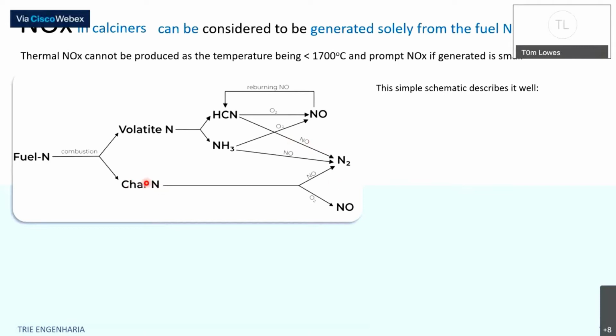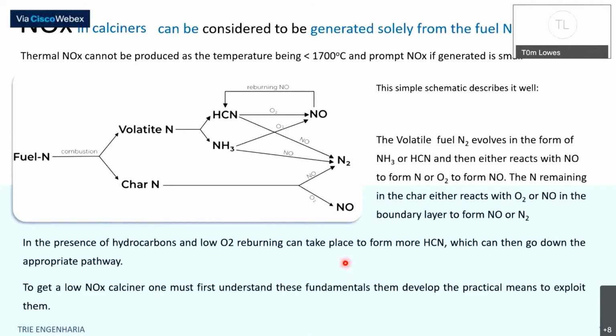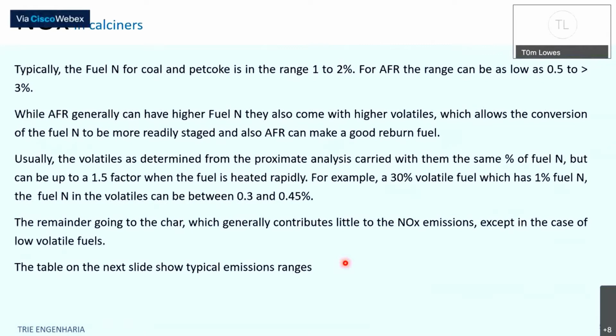The char is potentially a problem area on Petcoke and low volatile coals, not so much a problem for the normal bituminous type coals and even AFR. The char nitrogen, when it's evolved, will react with oxygen to produce NO, or react with NO to produce nitrogen. And with high specific surface area char, the contribution of char nitrogen to NO is around about 10%, but with low specific surface area char, typically of low volatile coals, you get a huge conversion of char nitrogen to NO, and that's the problem you have in India with your Petcoke. Typically, the fuel nitrogen for coal is between 1 and 2%. With AFR, it can be 0.5 to 3%. Generally, AFR has higher fuel nitrogen, but comes with higher volatiles, and therefore can more readily be reduced to nitrogen.